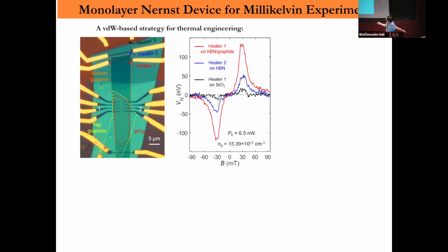So the key idea is to apply a temperature gradient through a gate. Here is a graphite narrow stripe that can be used both as a gate to tune the density of the flake, and also, because at millikelvin temperatures this is the only good thermal conductor, it provides a thermal gradient that's very reliable and robust.